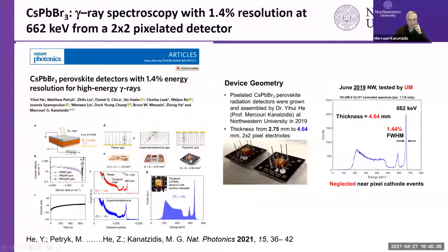So the planar detector shown here is detecting cesium gamma rays at 662 keV. And this is the spectrum. And this is good resolution for a planar detector. But then when we make the pixelated detector, the resolution went down for each pixel to about 1.44%. And so this was also very exciting because it points the way to larger detectors and more desirable detectors for particular applications. This was published recently in Nature Photonics.